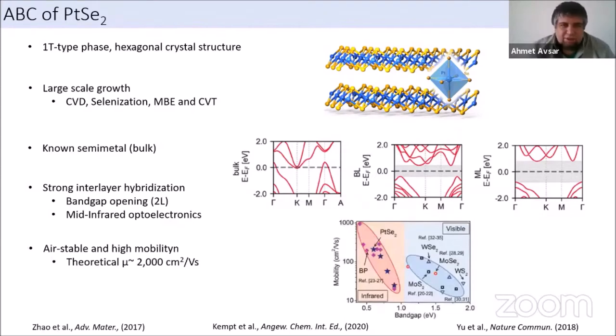Another promising thing about this material is it's expected to have very high mobilities. So it has a sizable band gap and high mobility, which could be quite interesting for transistor applications. And here you can already see that platinum diselenide falls into the category with black phosphorus. Black phosphorus is one of the most studied 2D semiconductors. And indeed, platinum diselenide is also in the same range of band gap and mobility.